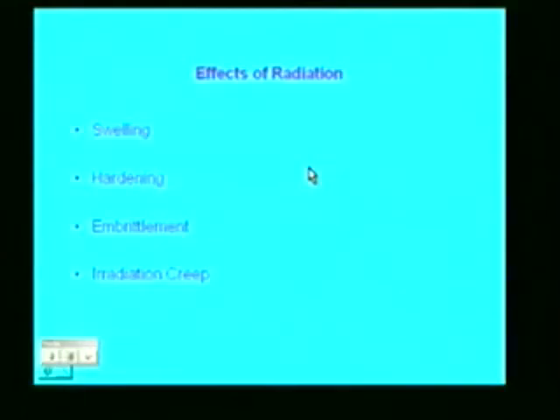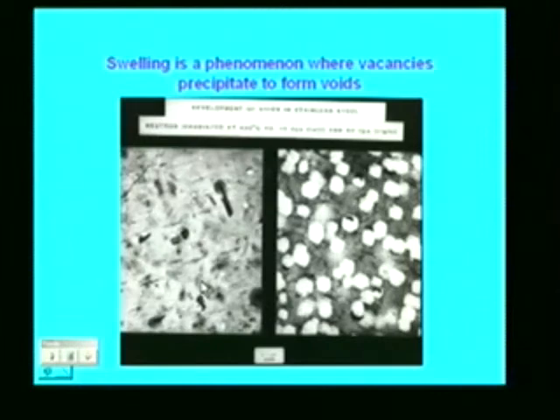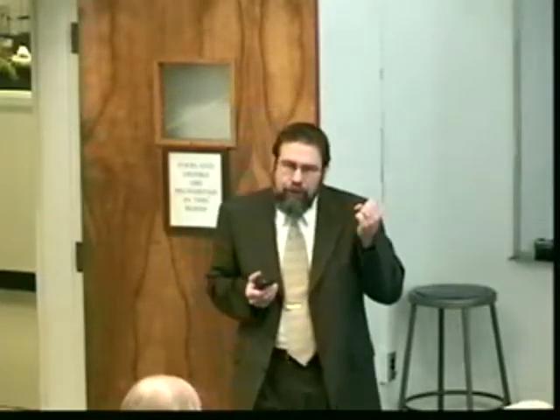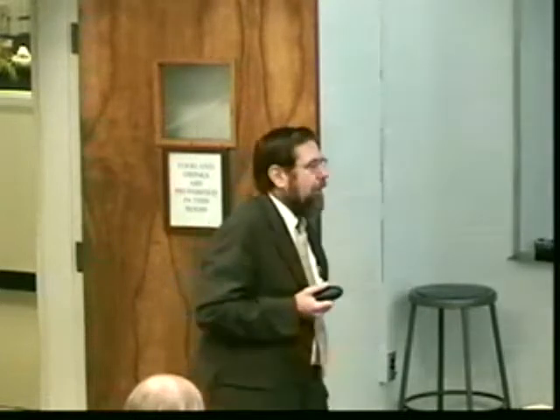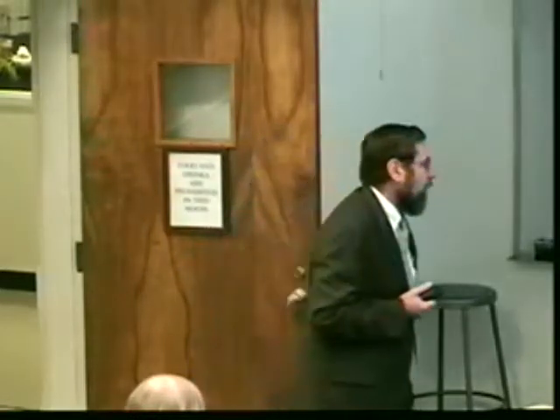So some of the effects of radiation, the most important ones, are swelling, hardening and embrittlement, which go together, and a rather interesting phenomenon, radiation creep. And I'm going to illustrate each of these. Swelling is a phenomenon where the vacancies we talk about precipitate and form voids. So they behave just like another chemical species, and a supersaturation of vacancies can lead to stable configurations of them, and they can grow as voids.